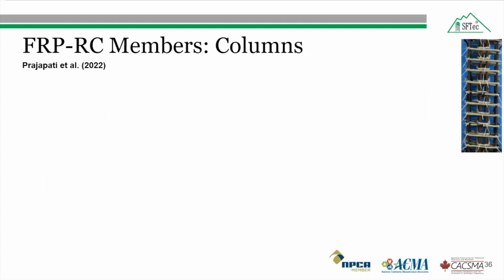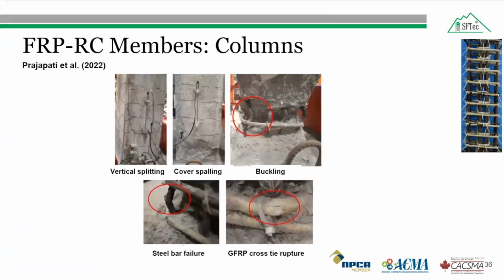So therefore, hybrid reinforced concrete columns consisting of longitudinal steel bars and transverse GFRP bars were constructed. The figure shows the casing of the hybrid reinforced concrete column, with longitudinal steel bars and transverse glass fiber reinforced polymer bars. The failure progression of the hybrid reinforced concrete column was rapid compared to the GFRP reinforced column, with the occurrence of all the milestones as in the GFRP reinforced concrete columns. Only here we can see the buckling of the steel reinforcement and the fracture of the steel bar, which was different from what we observed in the glass fiber reinforced polymer bar concrete column.